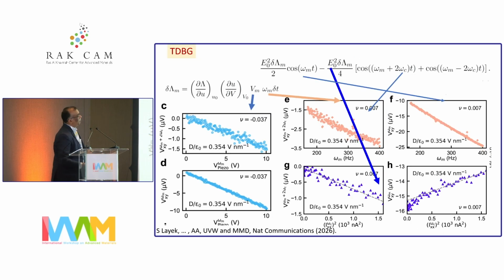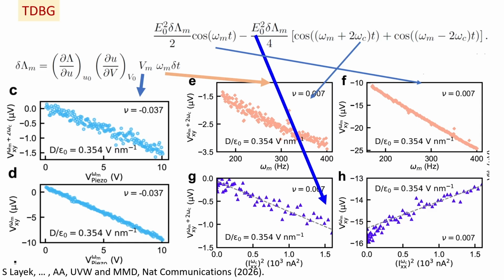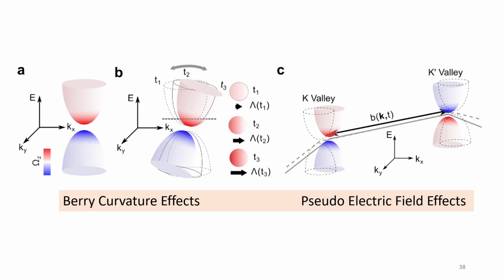So indeed, what he was able to show along with his students, Surat, is that the prediction we have is more or less verified in terms of quadratic dependence on applied field, as well as linear dependence on the frequency. But this interaction with experiment was very rich because it also told us that our theory missed certain peaks that they found. And those peaks were linked with the fact that graphene also can have pseudo-electric fields. The physical picture is shown here: these are the graphene bands, and these bands with the non-trivial Berry curvature can tilt, and that gives rise to Berry curvature effects.